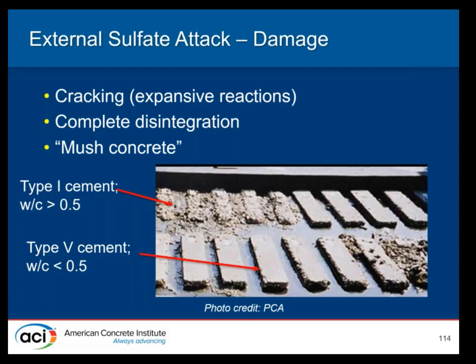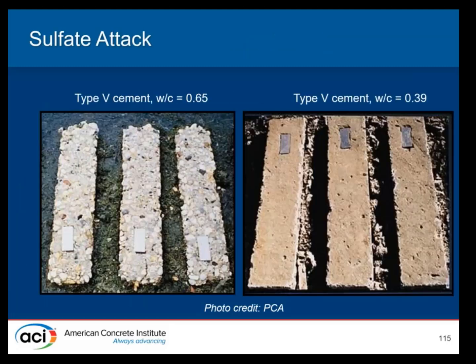The sulfate attack can be minimized by decreasing the water cement ratio so that the concrete's a little bit less porous, minimizing cracking so we're not giving a path for the nasty water to get in, and then selecting appropriate cement and other cementitious materials. So this gives you some more specimens of the same cement type with different water cement ratios. You can see how the specimens with the higher water cement ratio on the left are much more deteriorated than the ones on the right with the lower water cement ratio. Okay.